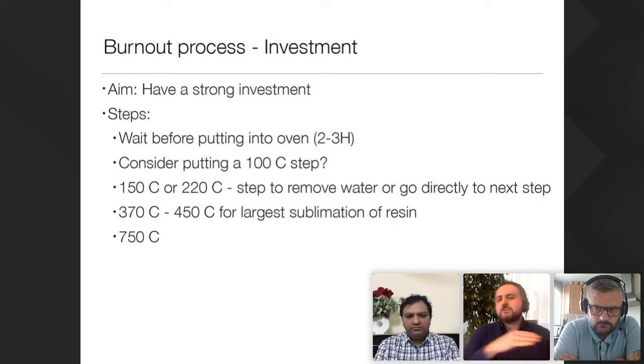So at 100 degrees Celsius, the water is not boiling yet inside the investment. If you put it in an oven at 100 degrees, because the middle is much less in terms of temperature, it will not boil, but what happens is that it will remove the humidity. So in that interesting paper, they put the investment in at 100 degrees for 2 hours, 3 hours - they make a step like that.